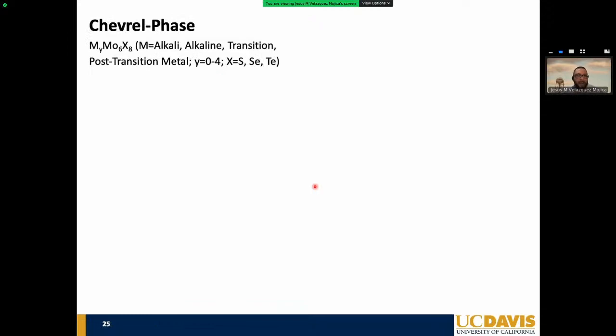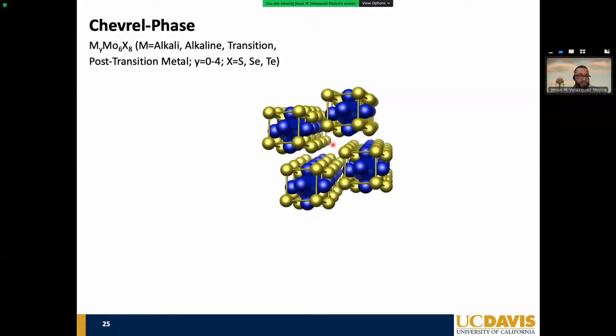So a little bit about this composition. This is highly known in the field of Chevrel phases. They've been studied for decades, specifically on the superconductor side of things, in terms of applications. And a lot of work done by Aurbach and Levi in the multivalent battery world. I think, like I showed you on the different coordinations between molybdenum and sulfur, they're just very versatile and flexible materials. And basically it starts with a molybdenum that is octahedrally coordinated, that is encapsulated within this nice little cube of chalcogens. And then when you look at the extended structure, you create these tunnels where you can intercalate things like alkali, alkaline, transition, post-transition metals. You can also change the chalcogen in the cage, okay? And you could also impact the stoichiometry of the metal intercalant from 0 to 4.